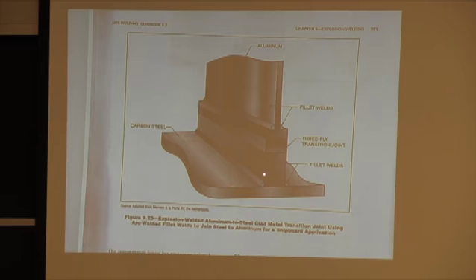So they have a steel base plate. They put one of these transition joints in here. This one happens to be a 3-ply one, so you add carbon steel to aluminum, and you just fillet weld the steel to the aluminum with one of these transition plugs. The only problem you then have is you now put a galvanic couple of aluminum and iron into a seawater environment, and it corrodes. Okay, it corrodes just great.